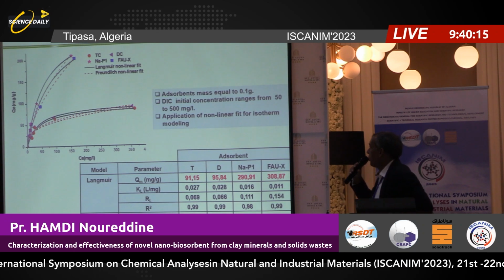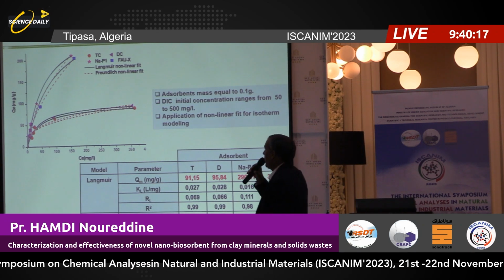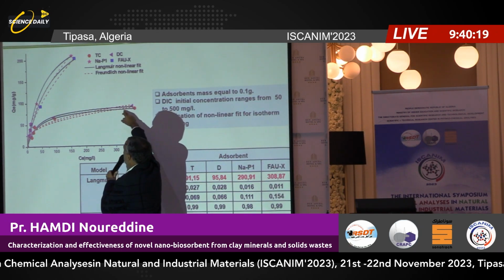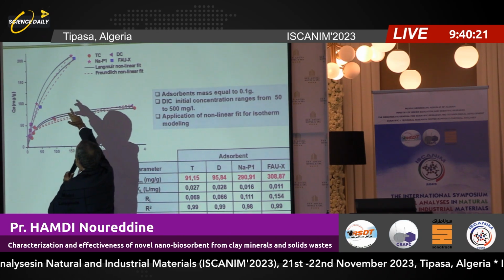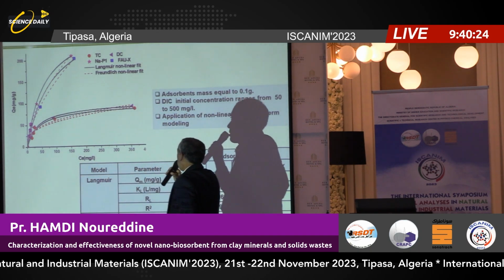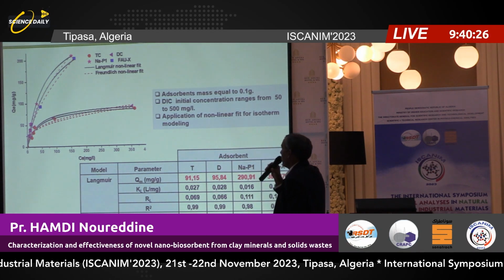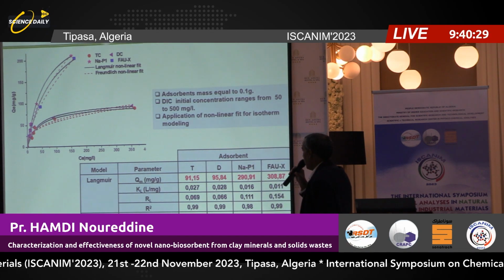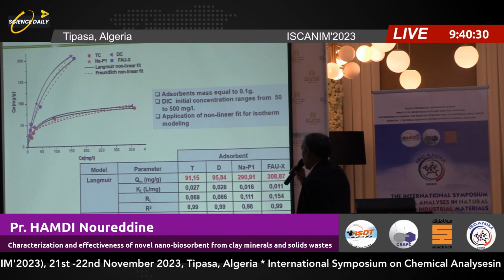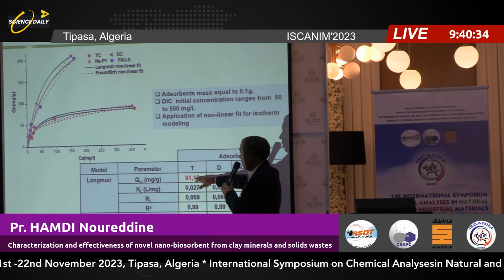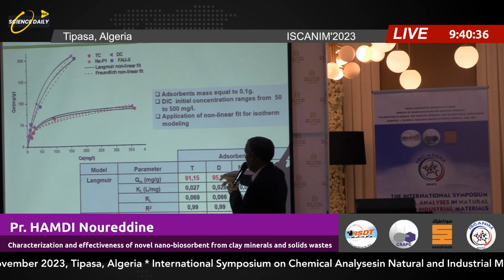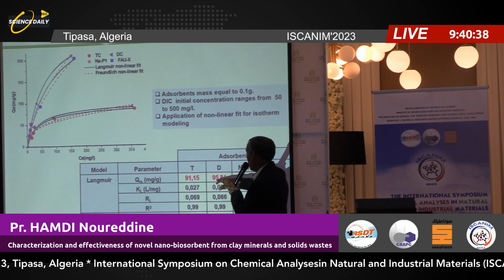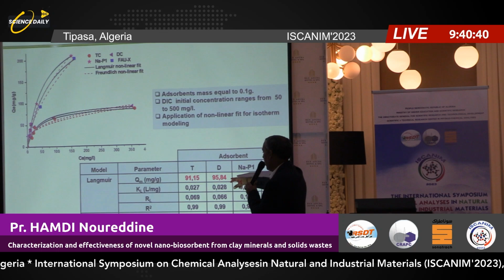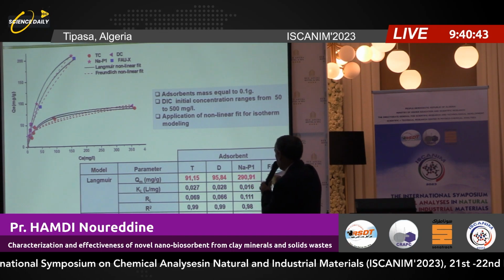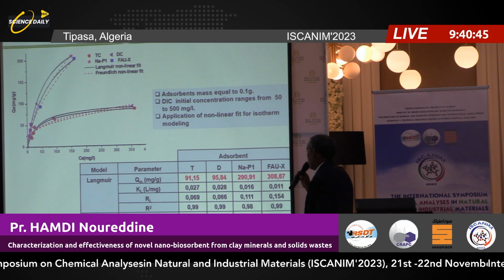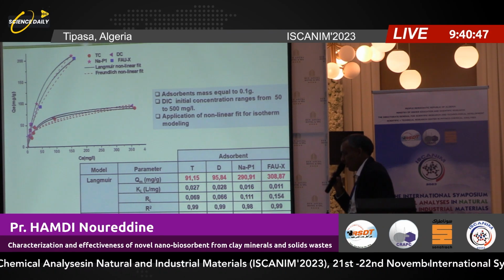The other term is the adsorption compared to the clay minerals. This is the adsorption of clay minerals, and both the zeolite P and the zeolite X. The adsorption capacity is very, very huge compared to the clay mineral. Here, for example, the clay mineral Tejra or the clay mineral Douiret, we have only 90 milligrams per gram, but in the case of zeolite, we reached 290 or 308.